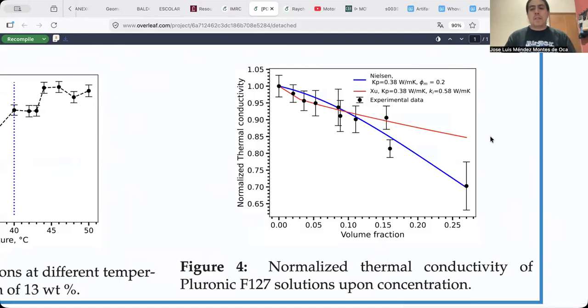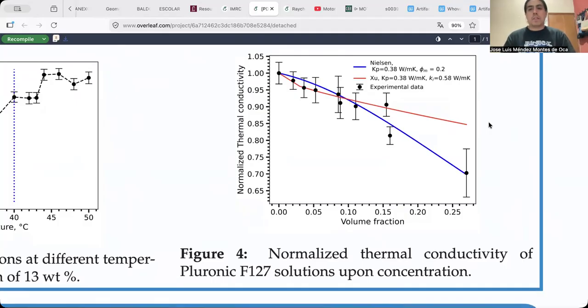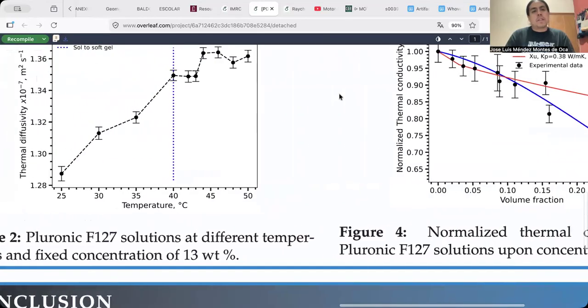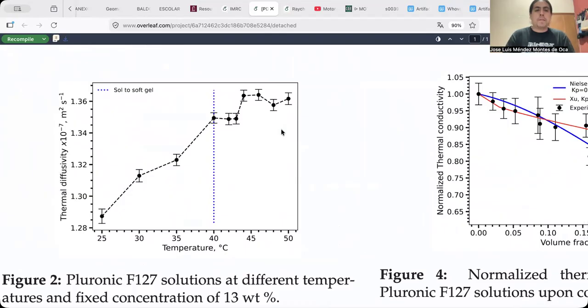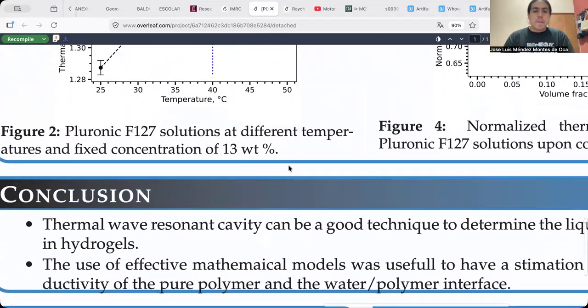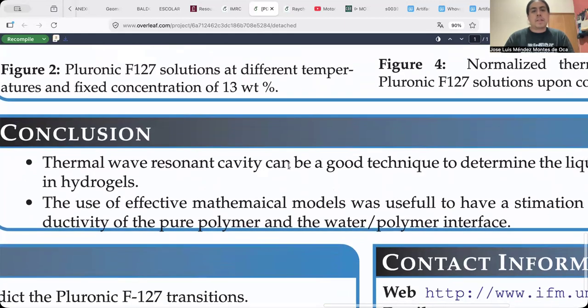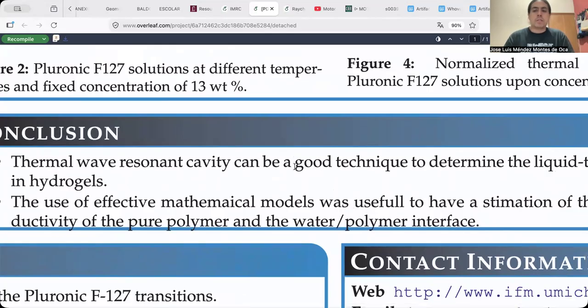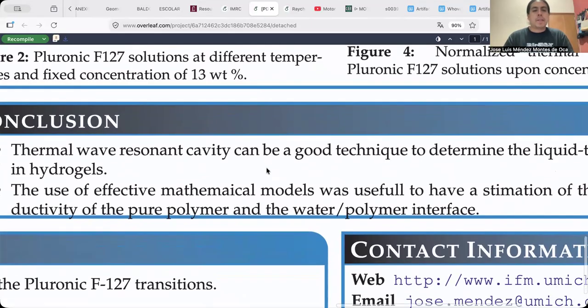So we are currently working on modifications of the Xu model to have a complete description of these transitions using some of the parameters found with the Nielsen model, and on the correct interpretation of the thermal diffusivity and conductivity of the experiment made upon temperature. And as conclusions, we consider that the thermal wave resonant cavity technique is able to observe the transitions of this pluronic hydrogel upon temperature and concentration, but effective thermal mathematical models are needed for a better description of these transitions.